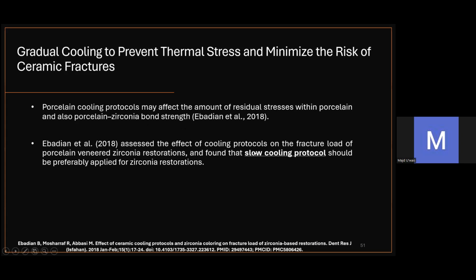Also, they assessed the effect of cooling protocol on the fracture load of porcelain veneer zirconia restorations and found that slow cooling protocol should be preferably applied for zirconia restoration. And the reason was attributed to the low conductivity nature of the porcelain. When you have rapid cooling for all ceramic, the superficial layer will lose its temperature or will have a sudden decrease in the temperature, while the inner, underlying layer is still warm, and this will create tensile stresses. And these tensile stresses may lead to fracture or debonding of the veneering porcelain.